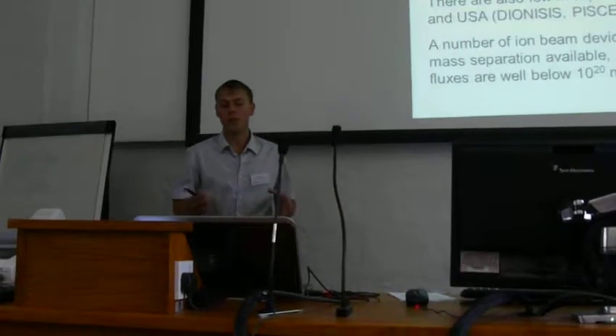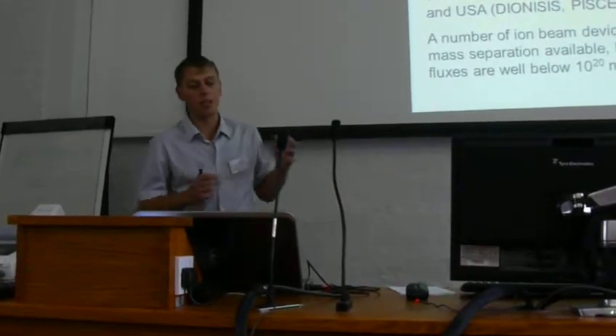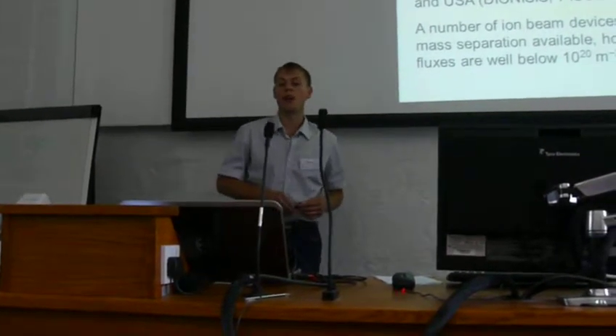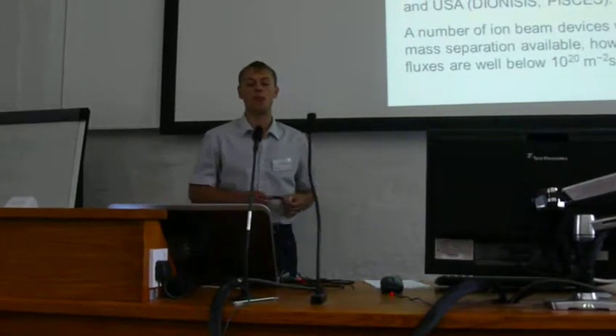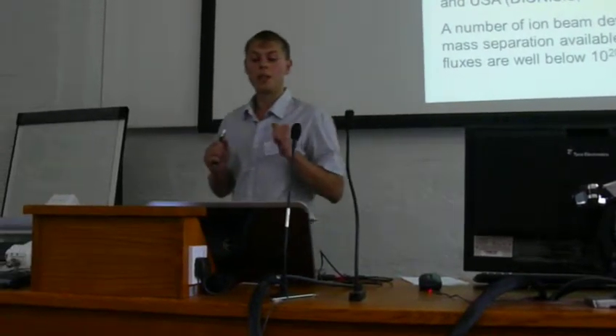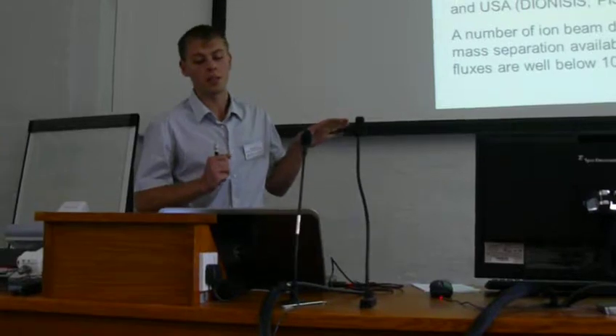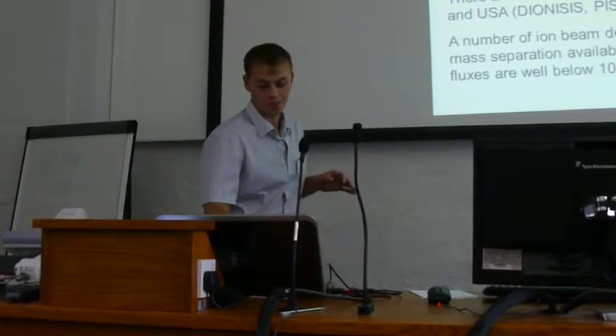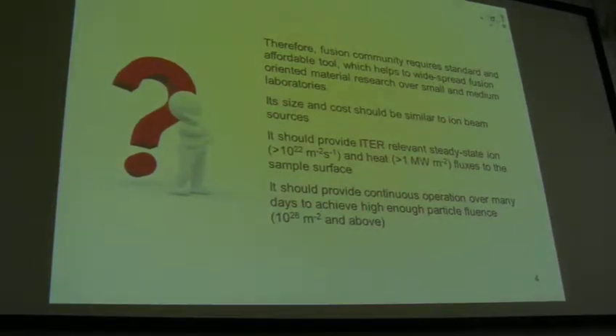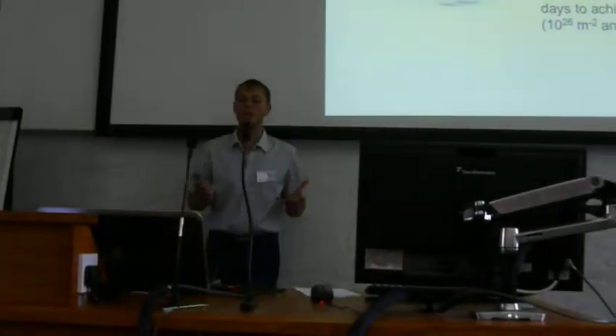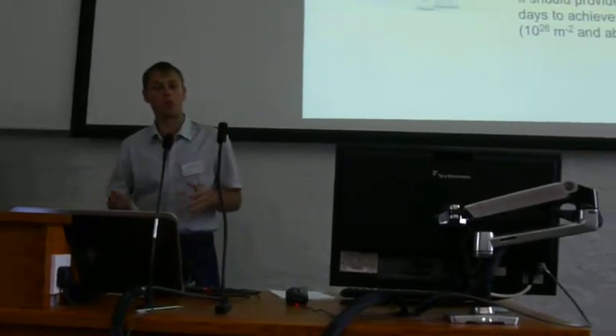There are only a few of them in Japan and the United States. Then there are a number of ion beam devices with magnetic mass separation available. However, typical ion fluxes are well below 10^20 particles per square meter per second. Therefore, the fusion community requires a standard and affordable tool which helps to spread fusion-oriented material research over small and medium laboratories.